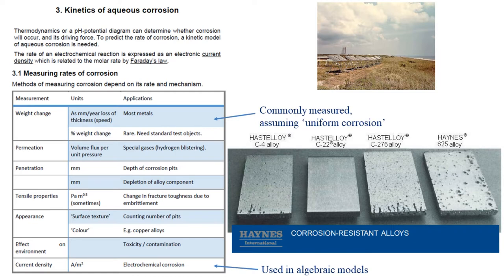Other specialist situations exist too. There are lots, so let's just list a couple. We could think about depletion depth in an alloy, in which one metal element, probably the more reactive one in the metal, might be lost from some surface layer down to a particular depletion depth. This could weaken the object. And because of this, or because of oxide growth on the surface, we could talk about a decrease in fracture toughness of some alloy. And in a specialist situation like that, we would need tables of experimental results about how a given alloy, its properties deteriorate under some particular environment.